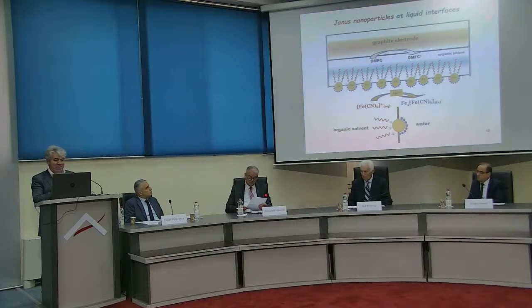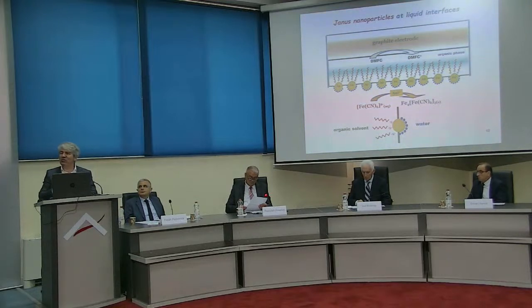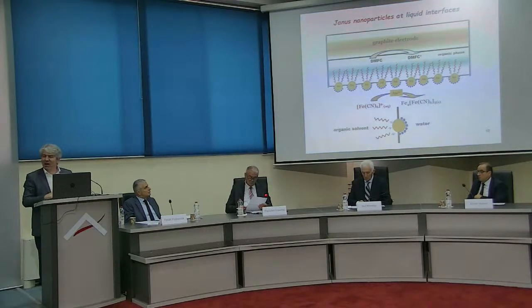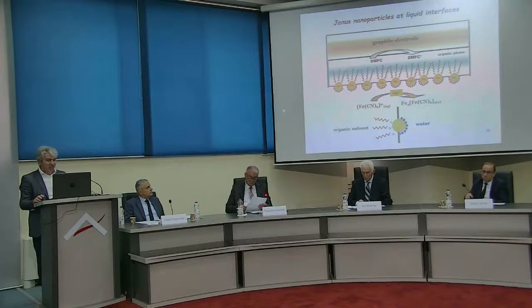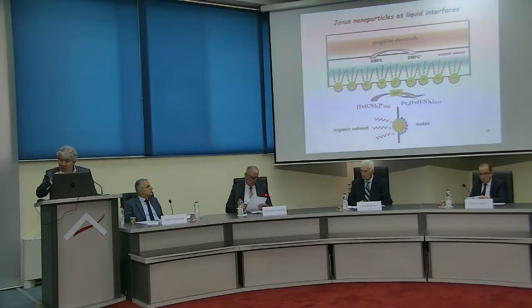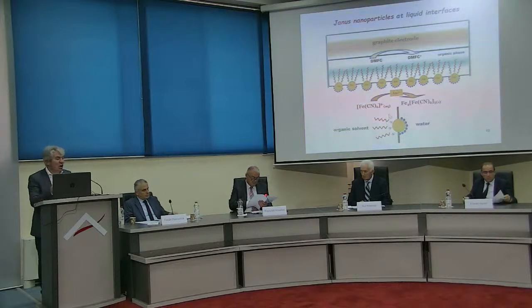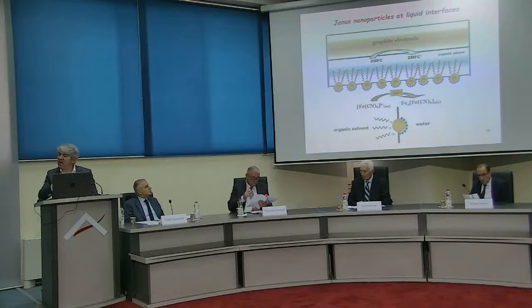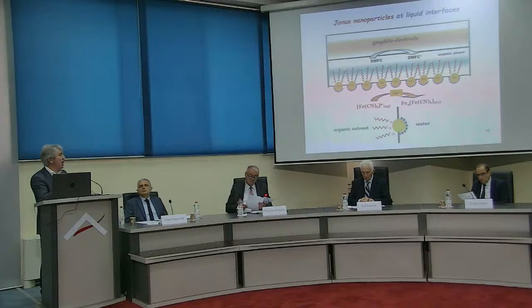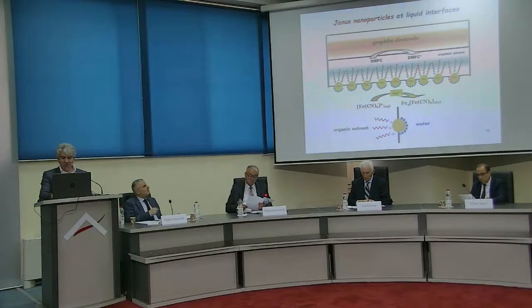Sometimes this modification could be even more sophisticated. Like this Janus particle, according to the Greek mythology, Janus with the two faces. This is a Janus particle, again gold at the liquid-liquid interface, but we have initiated hexacyanoferrate, Prussian blue actually, electrodeposition only from the side of the water. From the side of the organic phase, we have again thiol, and we have some composite, very interesting material, just as a proof of concept that we can create at the liquid-liquid interface some interesting particles. I don't claim that now they should be very useful, but as an experimental approach, that was very interesting.